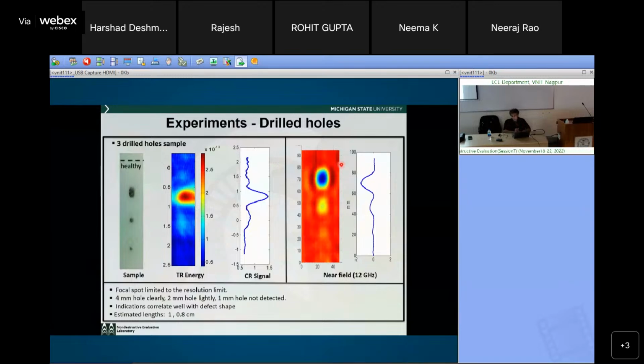At a much lower frequency, we are able to penetrate a couple of layers. And these Teflon inserts were in, I think, a 12-layer laminated carbon composite, and we were able to pick up the different layers with that. We did it at about 5 megahertz, pretty low frequency, not microwave by any stretch.